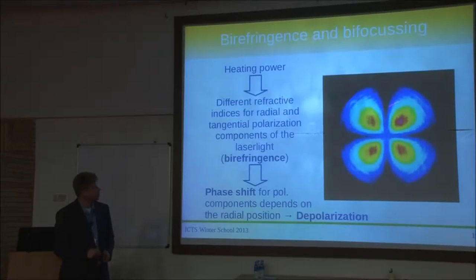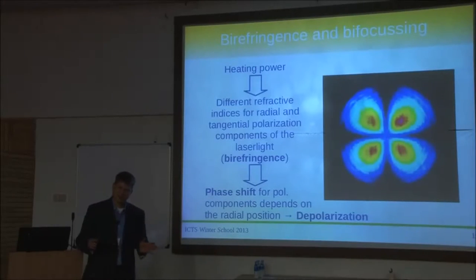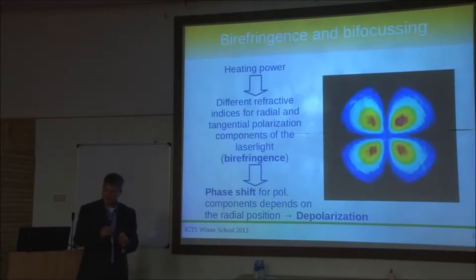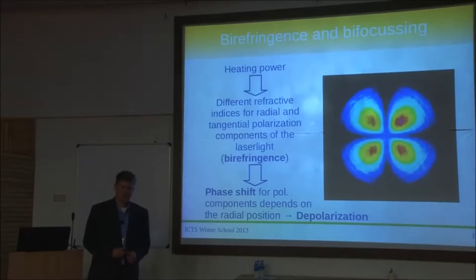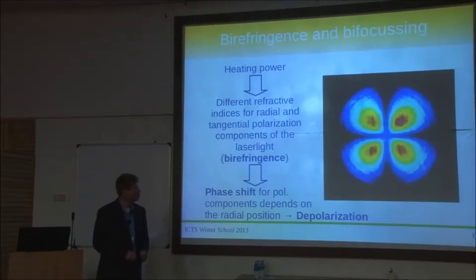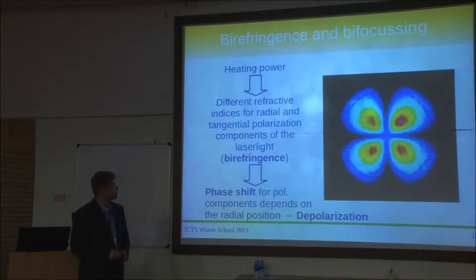I have a CCD image of depolarization: you send in a nicely round, polarized beam, pump the crystal, and look behind a polarizing beam splitter. You no longer get a nice round beam profile — you get this clover-like pattern. It looks artistic, but the LIGO guys asked us to build something with a nice round beam profile, so we had to put some effort into solving that.